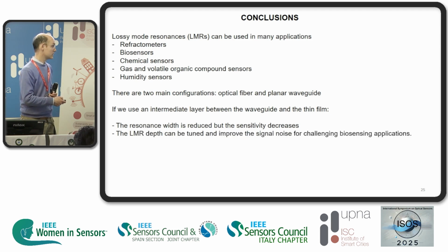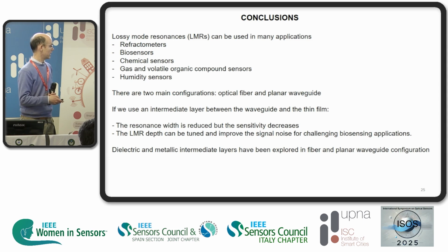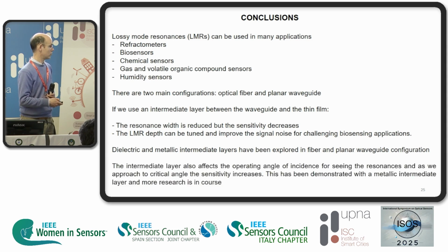The LMR, this is perhaps the most interesting point, can be tuned and improve the signal to noise ratio for biosensing applications. And we have explored this with dielectric and metallic intermediate layers. So the intermediate layer affects the operating angle of incidence, and if we approach the critical angle, we could increase the sensitivity. So this line is where we are working now, and we should improve this.